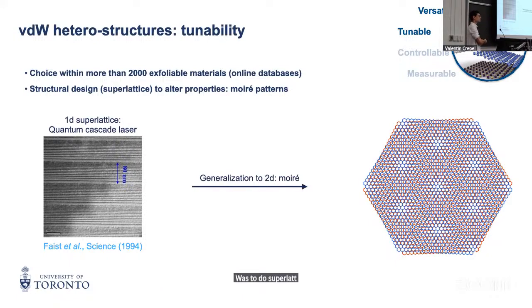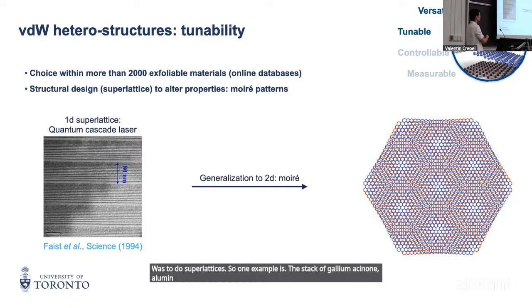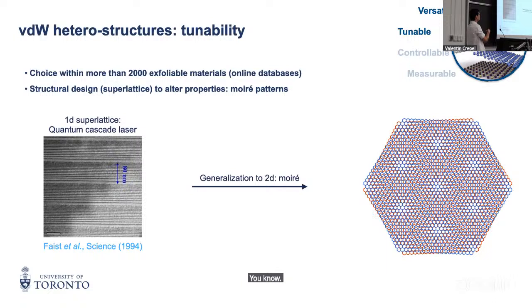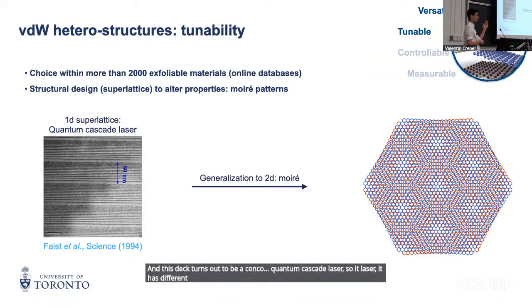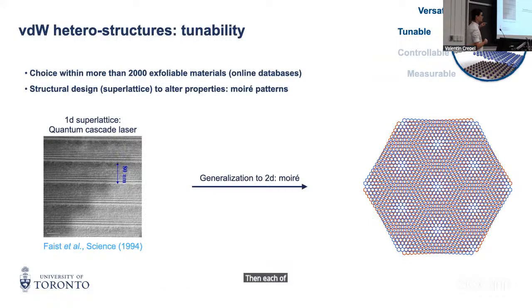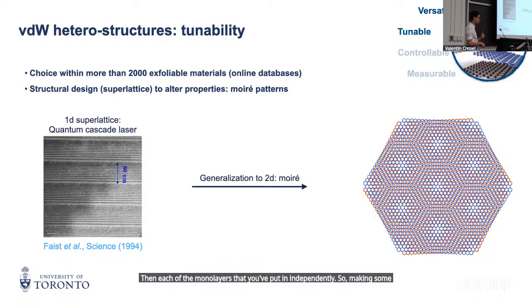So one example is the stack of gallium arsenide, aluminum arsenide that I showed above. Just stack them and do 1D superlattices out of them. And this stack turns out to be a quantum cascade laser. So it has different optical properties than each of the monolayers that you've put in independently. So making some superlattices brings out new physics at the forefront.